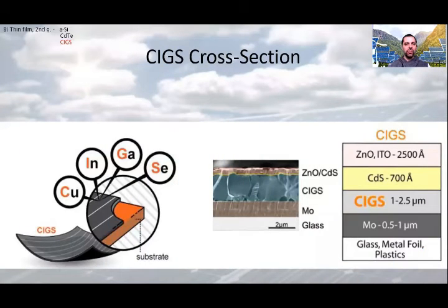The basic structure of a CIGS thin film solar cell can be seen on this image. The most common substrate is soda-lime glass of 1 to 3 mm thickness. This can be seen below. This is coated on one side with molybdenum that serves as a metal back contact.